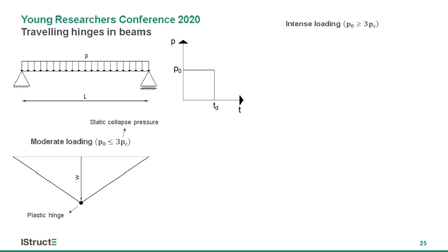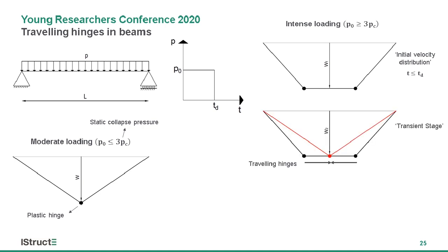Under short-duration pulses, however, ductile structures are expected to be able to resist loads significantly higher than the pseudostatic capacity due to the additional effects of inertia. To continue satisfying the material law under intense loading, this will result in two plastic hinges forming initially that will start traveling towards the mid-span location once the applied pulse has decayed. Eventually, the traveling hinges will transition to a final pattern that is identical to the stationary collapse mechanism under static or moderate dynamic loading.